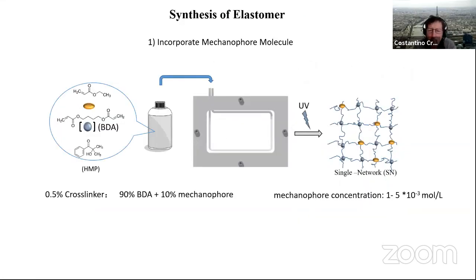So we made elastomers, and I'm going to show you a simplified picture here, but what we are doing is mixing the ingredients, including some of that yellow here representing the spiropyran, the mechanophore, and also another crosslinker. There is about 0.5% crosslinker in this network, so it's not very cross-linked. 90% is a regular one, giving you carbon covalent bonds, and 10% is this mechanophore crosslinker. We hope that it's distributed randomly. Now, if you take one of these networks and you try to pull on it, it will break very locally, and you will activate the molecule very locally. I'll show you that we can still get information, but it's not the easiest way.